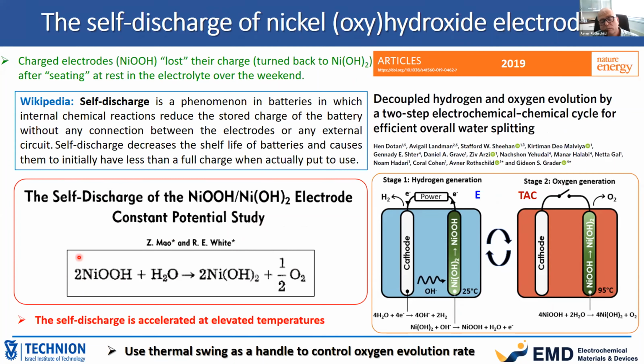And indeed, we dug into the literature and found that it's very well known in the battery world, a phenomenon called self-discharge of the charged nickel oxyhydroxide. It has a spontaneous chemical reaction with water that produces oxygen. And the point is, this reaction occurs very, very slowly at ambient temperature, but you can accelerate it by heating. So now we have a handle to control oxygen evolution at high temperature, and we can shut down this path by keeping the system at low temperature, at ambient temperature.